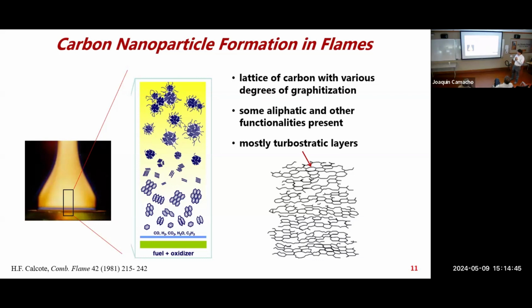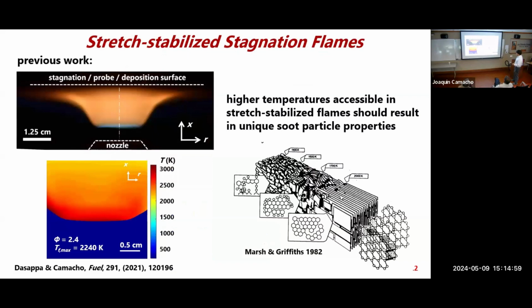This has been studied for a long time to aid soot formation research, which leads to cleaner burning engines, to try to avoid emissions and things like that. When we have these higher temperature flames, we should indeed expect that the structure of the particles, the carbon material itself, should have a different crystalline structure than typical soot. And if it's high temperature enough, perhaps it will even evolve into graphite, graphene type structures.